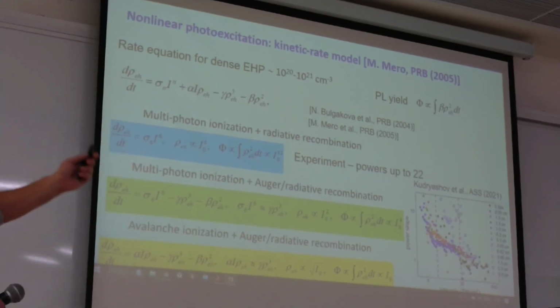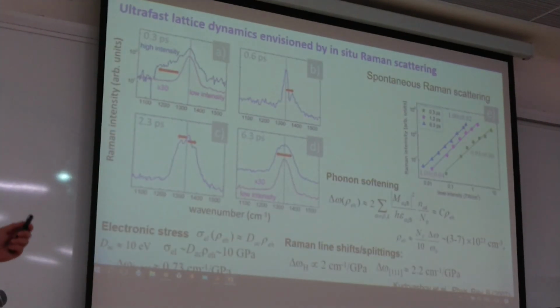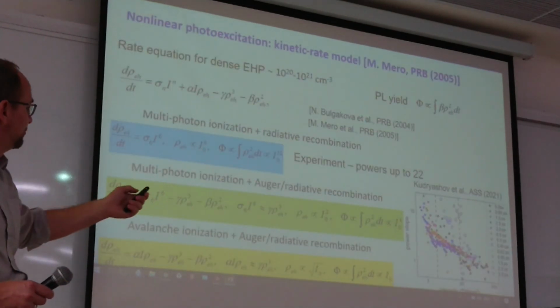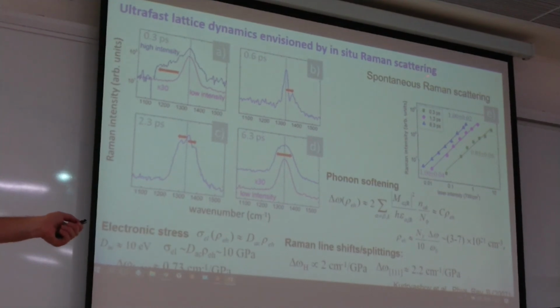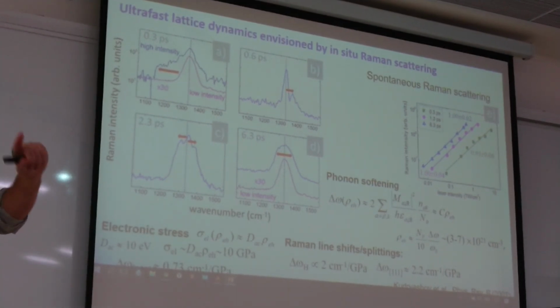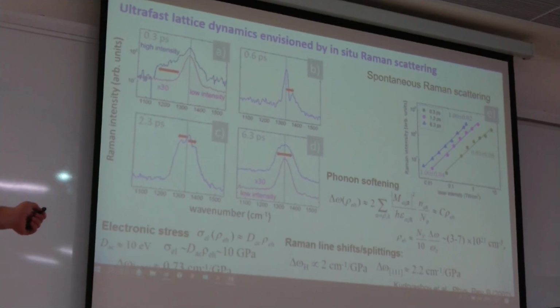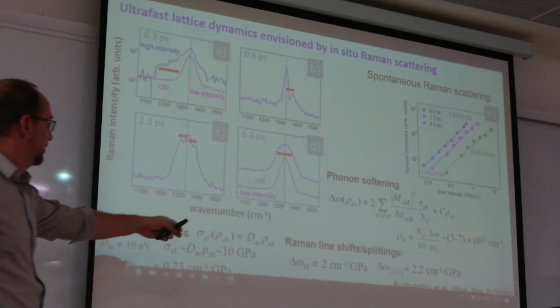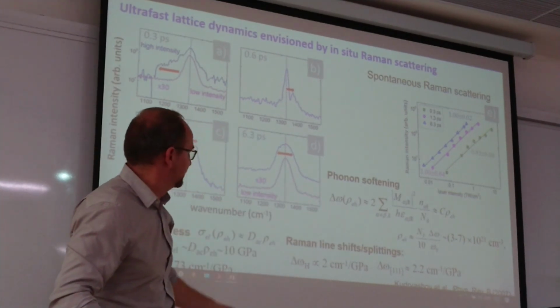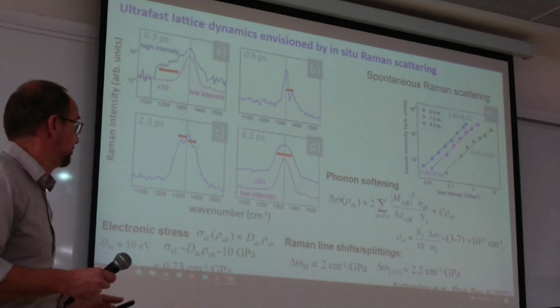This is a simple kinetic rate model which explains the solid state dynamics, but I will skip it. What we can do also to understand this process is in situ Raman scattering. The same laser pulse which promotes electrons can produce a Raman signal, and we can detect this Raman intensity and see how it changes for different pulse widths. Initially, it's strongly broadened to the red wing, and this shows the phonon softening because of plasma. And so we can evaluate the concentration of plasma from these measurements.